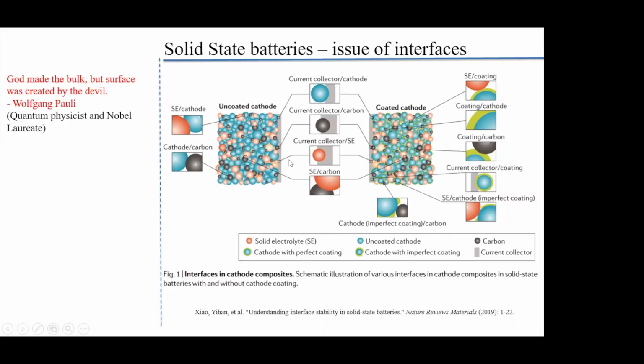So lithium has to have impeccable diffusivity through all these interfaces. You need to improve many of these, make sure the interface is conducive for lithium transport at a fast rate, so when you floor the gas pedal, it is able to give that energy. That means lithium is trying to pass through all kinds of interfaces here. So the more interfaces you have, the harder the problem gets. This is from the paper Understanding Interface Stability in Solid State Batteries, in a pretty prestigious journal. People can go into this journal paper and read more about it.